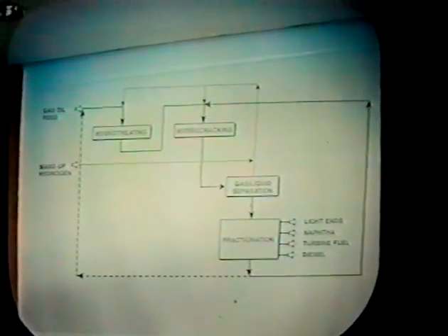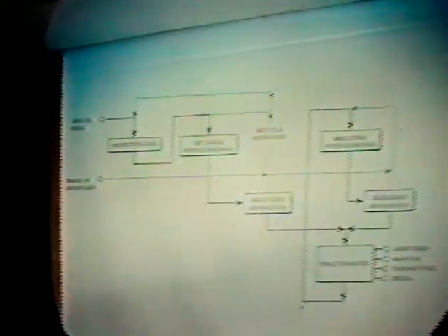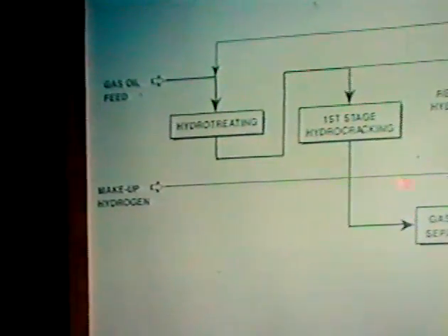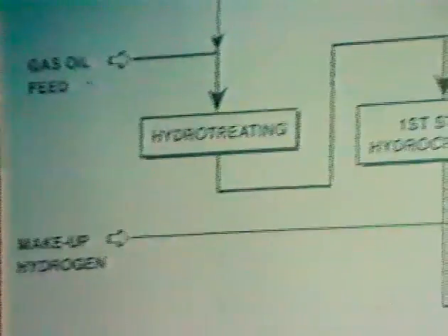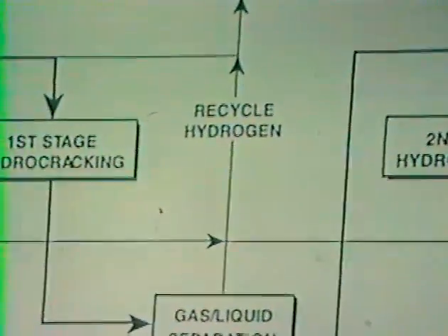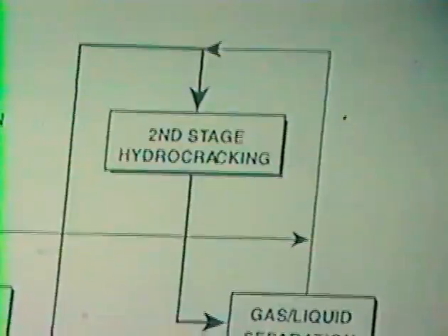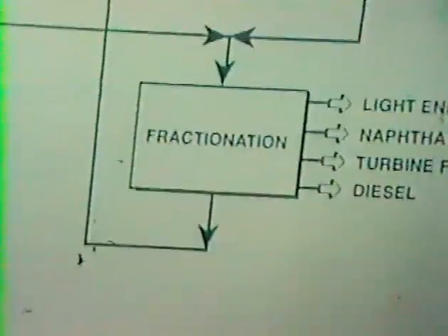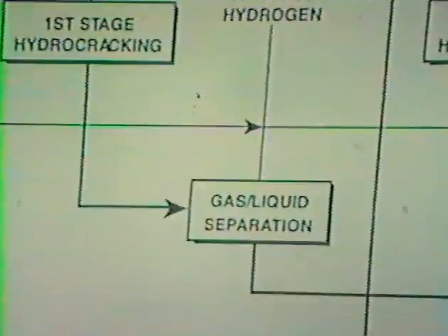This reactor usually runs about 70% conversion. And the reason I'm showing it here is that at this point, entering the cracking reactor, you have a feedstock which contains substantial amounts of hydrogen sulfide and ammonia. So the catalyst is always operating in this atmosphere. A modification of this process adds a second reactor, and for simplicity takes the product from the first reactor, which hasn't been converted into lighter boiling materials, and passes it through a second reactor. The difference in this reactor is the ammonia has been removed from the system, so the catalyst is operating only in the presence of hydrogen sulfide.